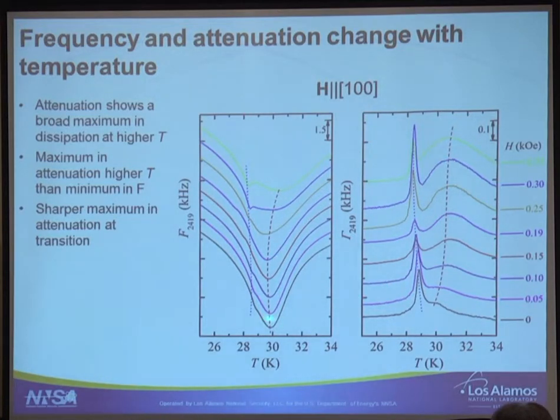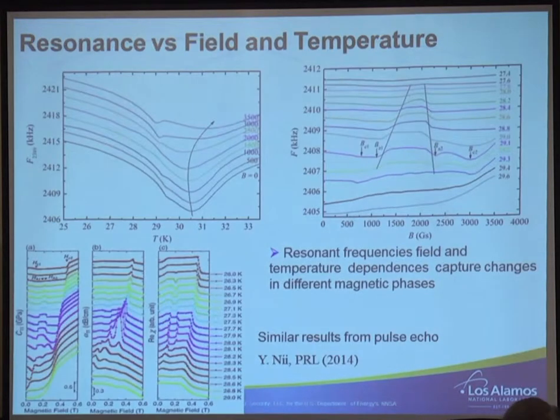So we can see the first transition, and also we can see the transition into the Skyrmion phase, as this will leave in the frequency a big peak in the attenuation. We can also do field dependence of the frequency, and here the presence of the Skyrmion phase is way clearer.